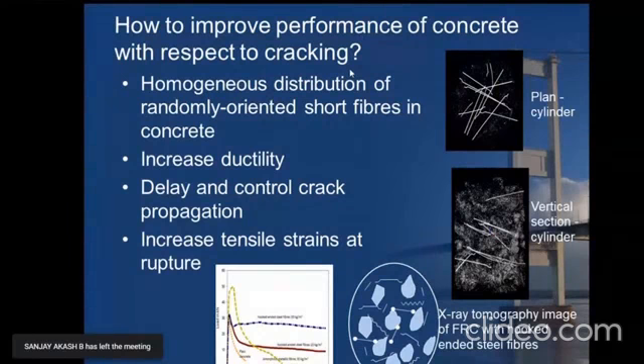I've just given you the test results and the tomography image analysis that can be used to find out the dispersion of the fibers in the hardened concrete. Maybe in a fresh concrete state, we will be able to see where the fibers are dispersed. But after mixing, after placing the concrete or after vibrating it, we will not get an idea of how the fibers are dispersed. So this is one of the non-destructive tests. We generally use X-ray tomography to get an image analysis where we will be able to locate the fiber dispersion in the matrix. So these are some of the images that I would just give to enhance the properties of fiber reinforced concrete.